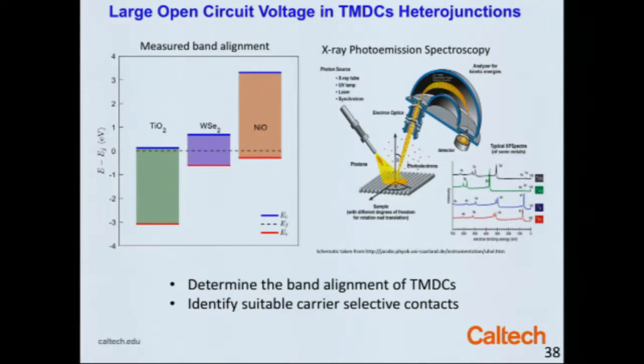So we searched through essentially the entire database of materials that have been studied for thin film solar cells and did photoemission spectroscopy. We measured the band offsets by photoelectron spectroscopy and found the work functions for nickel oxide and titanium oxide, and we're able to identify these as being useful materials.